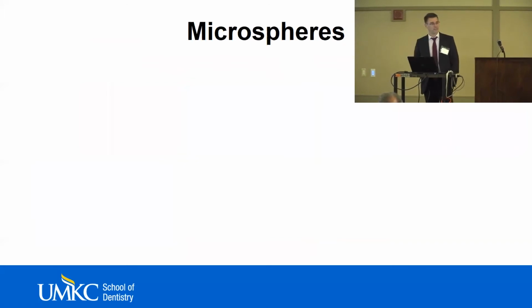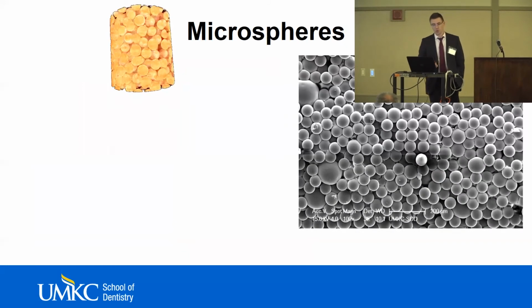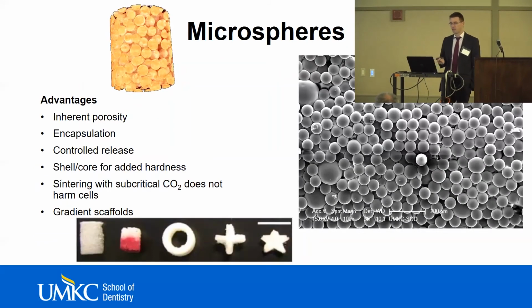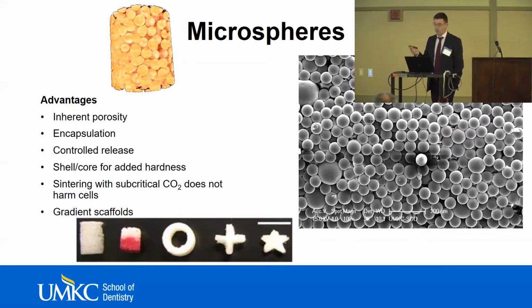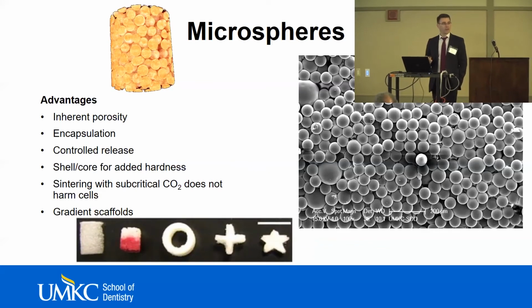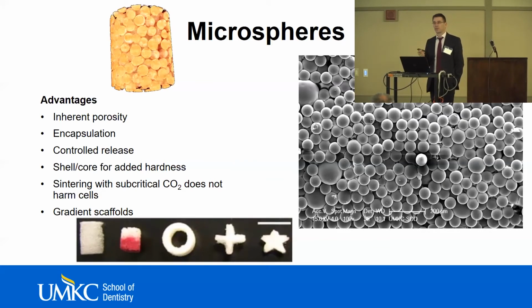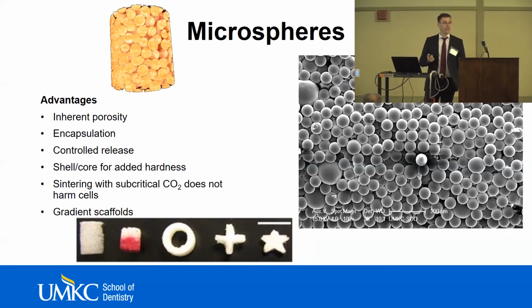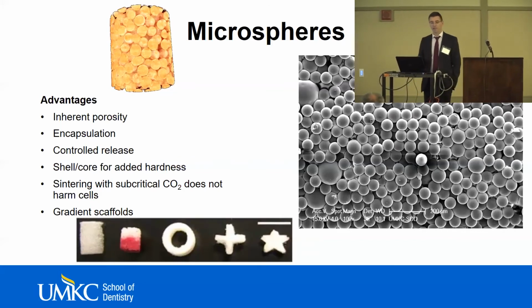So far for the process, let's get to the materials, or rather the shape of the materials. I think microspheres are very good to utilize in scaffolds for tissue engineering. So when these microspheres are packed together to form a scaffold, they have an inherent porosity due to the gaps between the spheres. The manufacturing process of the microspheres allows us to encapsulate growth factors, secondary phases of the polymers, drugs, or even cells. And by the biodegradation, we can actually release those drugs or secondary phases in a timely manner after implantation of the scaffold.